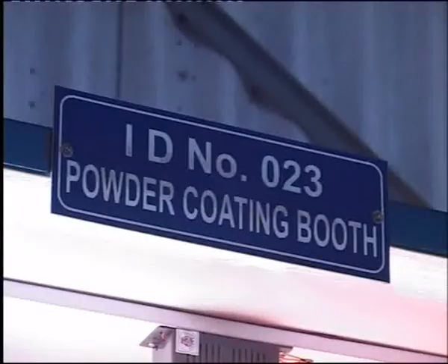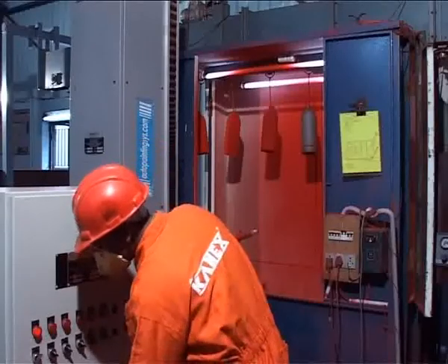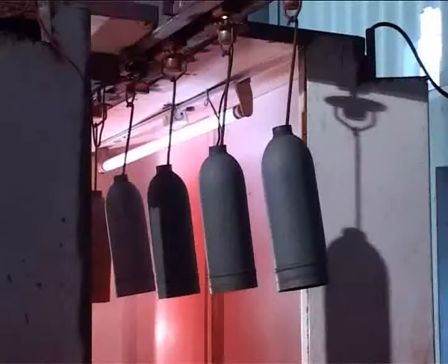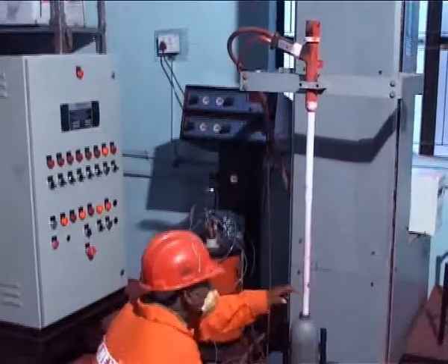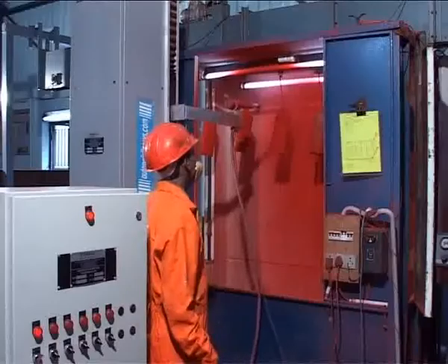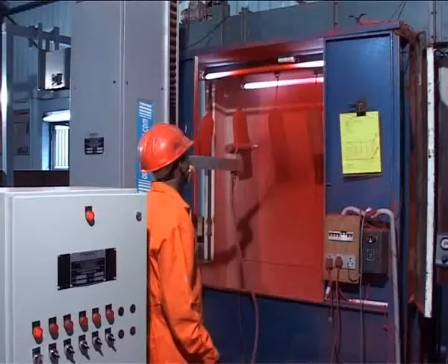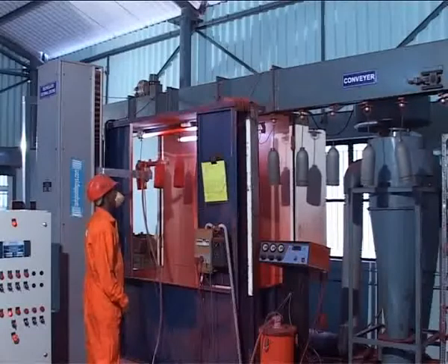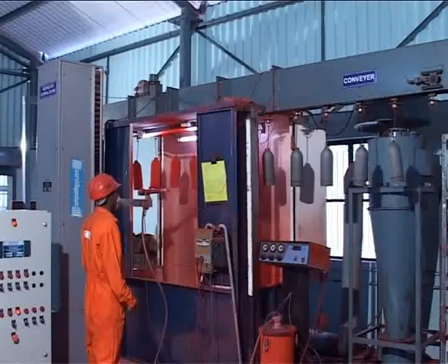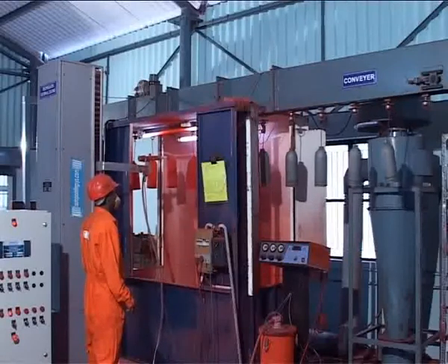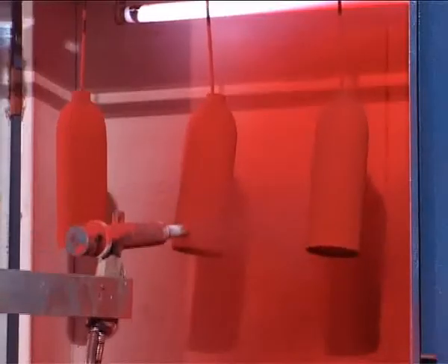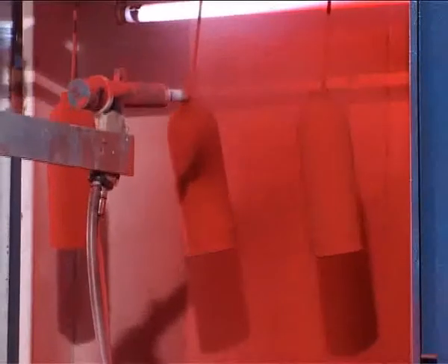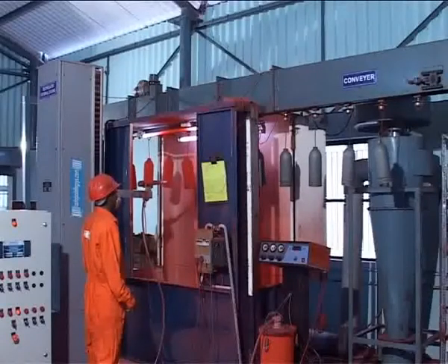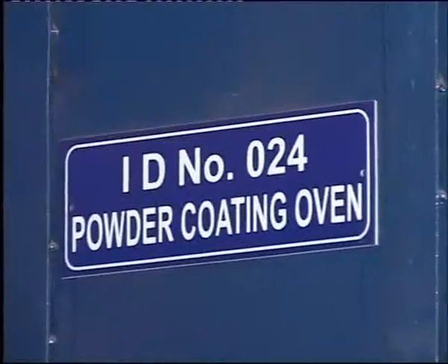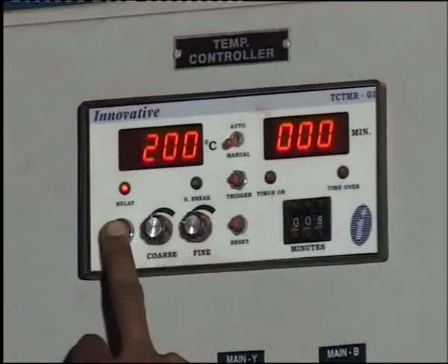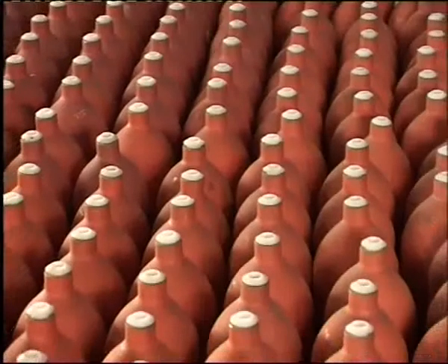KANEX has its own powder coating unit, which has an advanced efficiency of powder coating, powered by an internal and external coating reciprocator. Some of the advantages of these are an increased uniformity and consistency of powder coating, a smooth, swift and precise movement of speedy and uniform coating. It reduces powder consumption and cures in ovens at 200 degrees Celsius for 10 minutes.